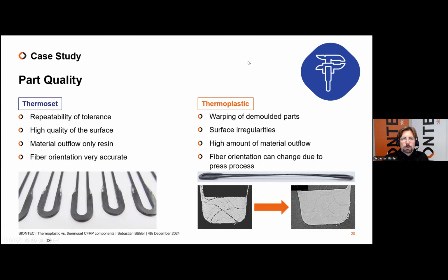Coming to the part quality, of course, the thermoset part quality is our classic way. We are very familiar with that, and the repeatability of the tolerance is very, very high. We have a very high quality of the surface, as you can see in the picture below. The only material we lose is the outflow of the resin, and the fiber orientation, because in that case we use a very low pressure for the injection, we have a very precise orientation of the fibers.